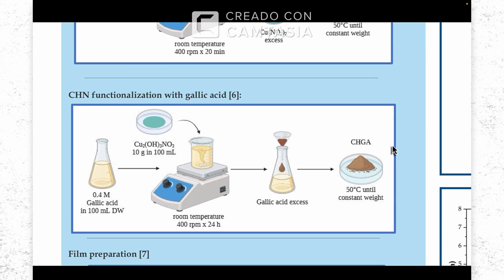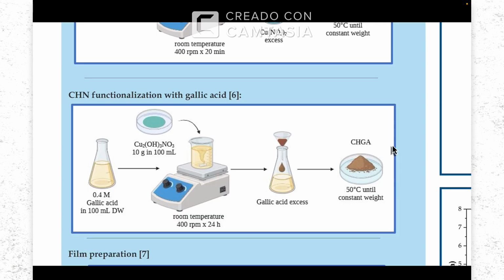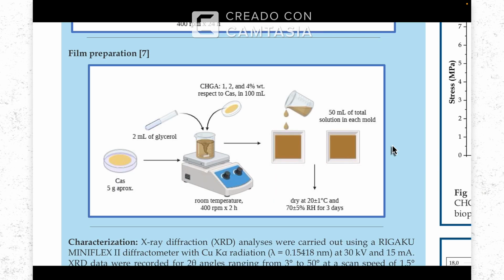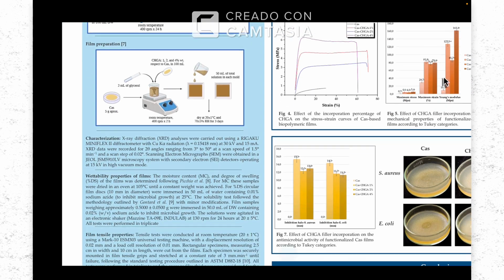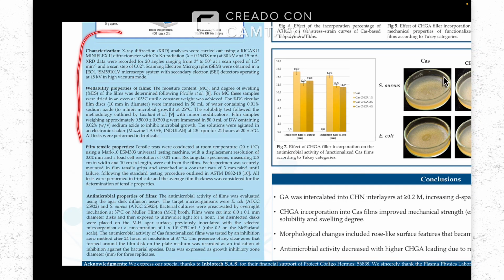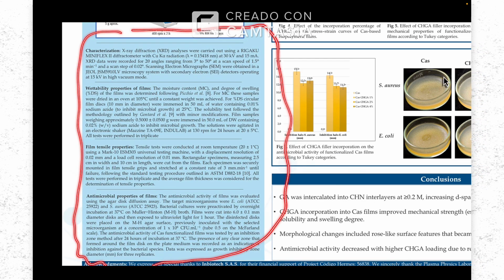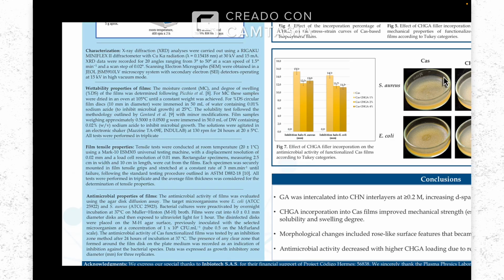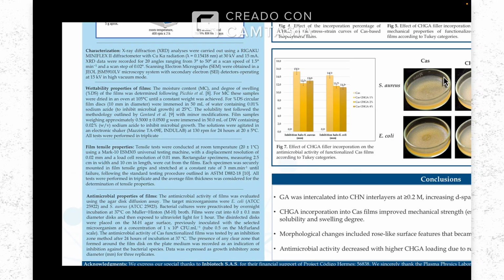After we obtain the material, we make a functionalization with gallic acid by a direct and simple method. Finally, we incorporate the functionalized materials in the films by a film casting method in concentrations of 1, 2, and 4 weight%. Here you can find the details for the characterization and the measurement of the different properties of the films.